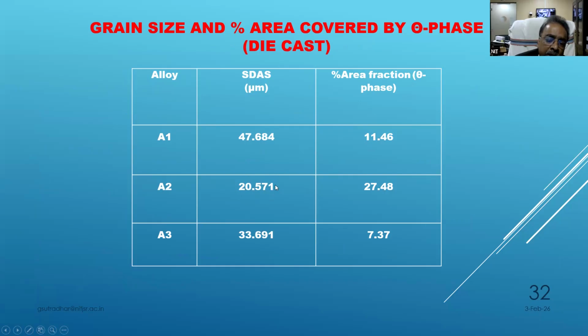If it is lowest, that means very close contacts, or you can say the grain structure will be very close and compacted, and you will get tightness. So as the tightness is there, you see the property and area of the theta phase. This is the element Al2Cu, and its percentage in the matrix is 27%. In other cases where the copper is 4%, the dendritic arm structure has a bigger size, but the area fraction is also less. It is again a little less at 11%. So 8% gives the best results.